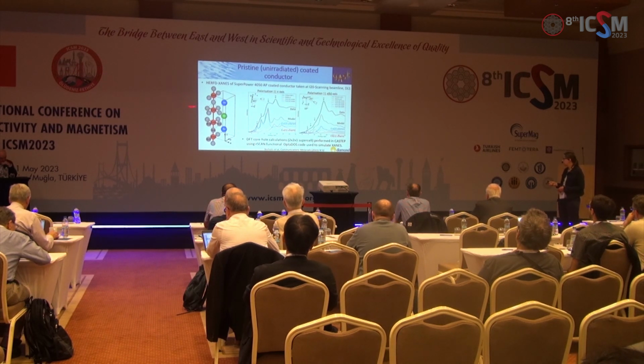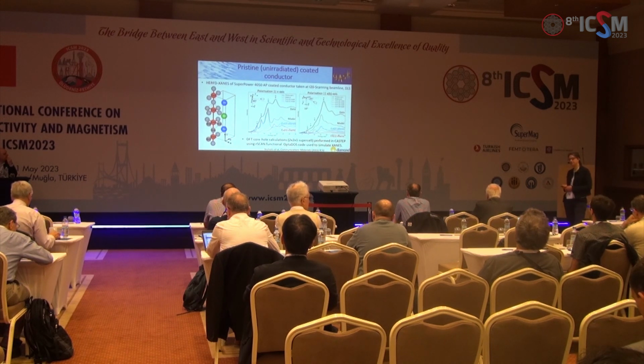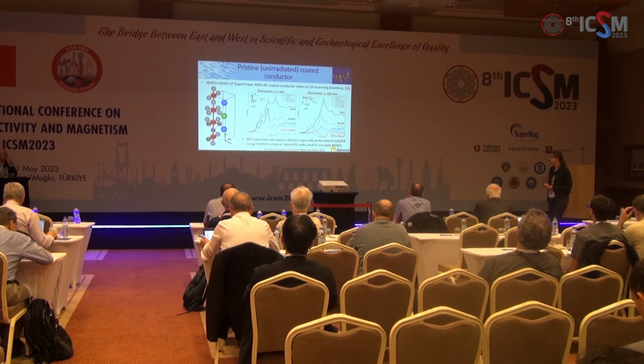What you can see is that we get all these features, lots of different features along this edge. It's not just one feature where we get the absorption. So understanding what's causing those is quite tricky, and to do it we need modelling. And we've used density functional theory to model this absorption process using core hole calculations.